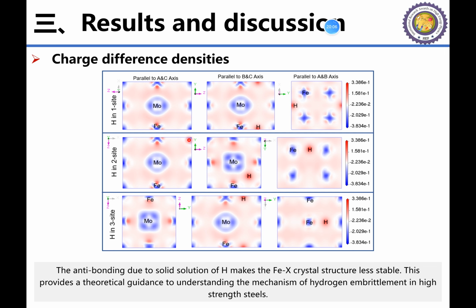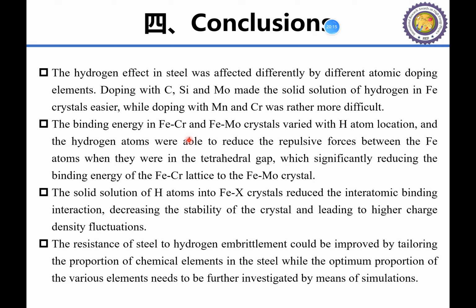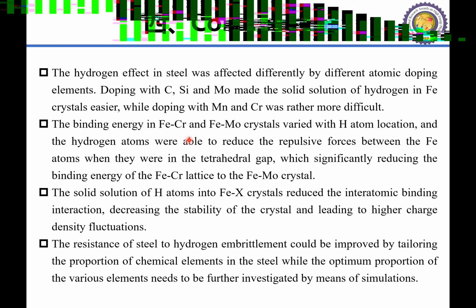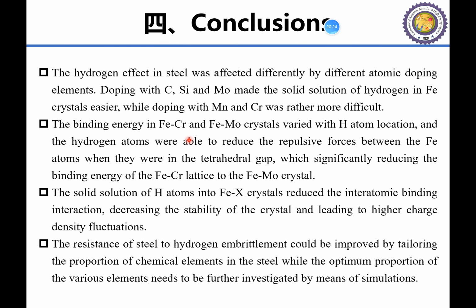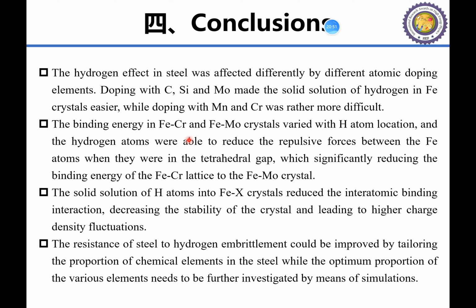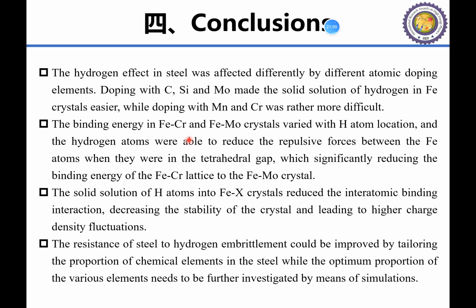And as the conclusions, the hydrogen effect in steel was affected differently by different atomic doping elements. Doping with carbon, silicon, and molybdenum made solid solution of hydrogen in iron crystals easier, while doping with manganese and chromium was rather more difficult. The second is that the binding energy in Fe-Cr and Fe-Mo crystals varied with hydrogen atom location, as the hydrogen atom was able to reduce the repulsive forces between the iron atoms when in the tetrahedral gap, which significantly reduced the binding energy of the Fe-Cr lattice to the Fe-Mo crystal.